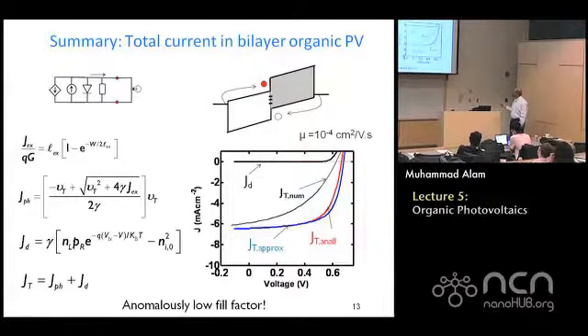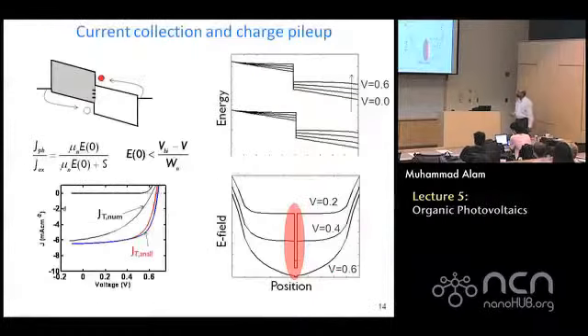You can immediately see this has a horrible fill factor, right? Fill factor is, remember, because the analysis people are lazy, this green small box that you set in with respect to the big box. Here the fill factor is actually pretty low, 0.5, maybe even 0.5 or 0.6, pretty low. And you can easily understand what happened, and that's why you should not be using planar junction most of the time.